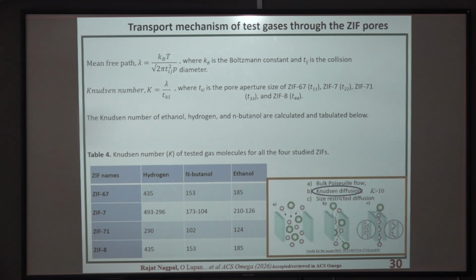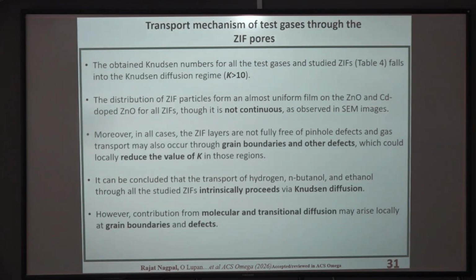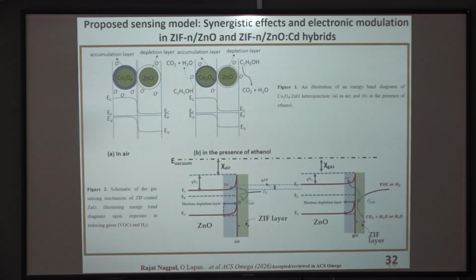What is its physical meaning? The particles and molecules will collide more with the pore aperture holes compared to interparticle collision. As we have already observed, ZIF layers are not continuous, so contribution may come from defects or grain boundaries, which will reduce the value of K. But intrinsically we can say it proceeds via Knudsen diffusion, though if contribution comes from other regimes, molecular and transitional diffusion may also contribute in their own way.